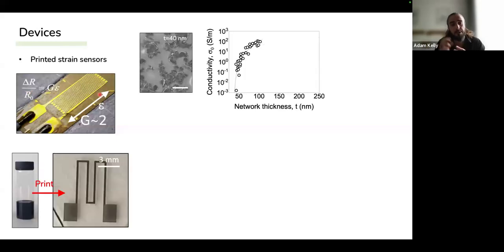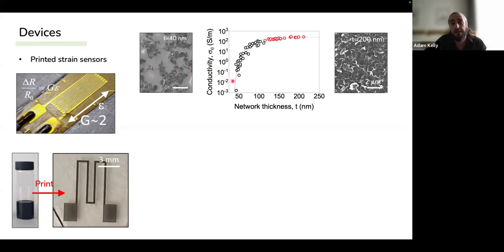So what we did is we took our dispersions, we took our graphene inks, we printed them, and what we found is that as the network thickness increases, the conductivity increases because of percolation effects. You can see here for low thicknesses of about 40 nanometers, we don't have a continuous network, so the conductivity is low. And then up above a certain thickness, the network becomes complete, and the conductivity tends to saturate because we have a bulk-like regime.